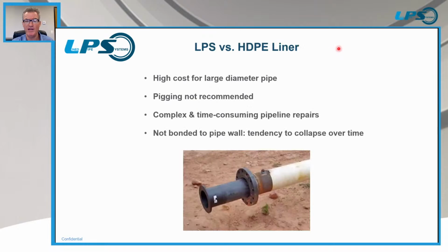The HDPE liner. When they came out with this a long time ago, this was the best solution to the problem. Really, it's primarily used on 18-inch and smaller pipe. You do sometimes see it in larger pipe, but the costs go up dramatically as you get to larger diameter pipe. There are some other major issues, and one is that pigging is not recommended. It stresses the liner and can cause it to sag off the pipe wall.